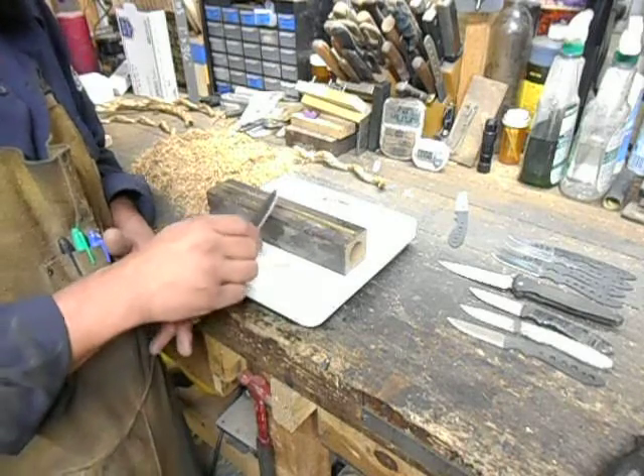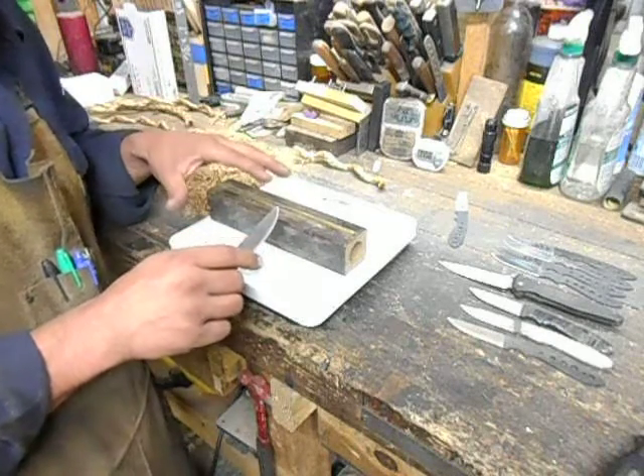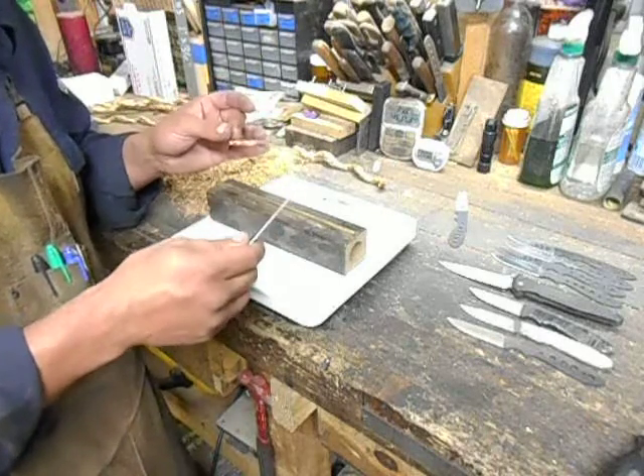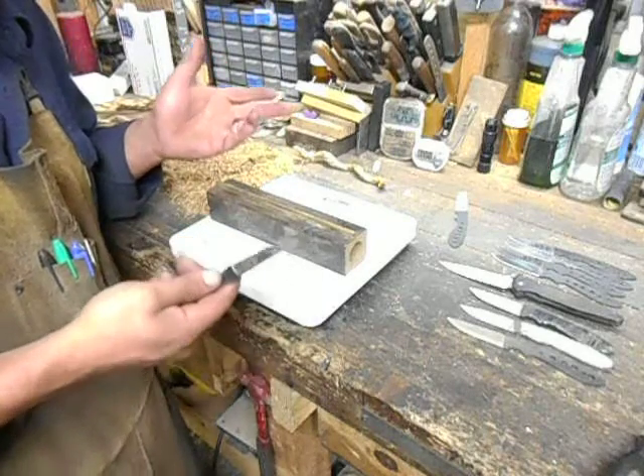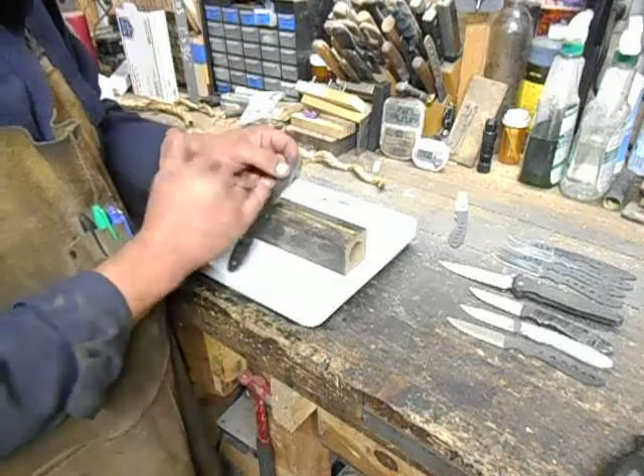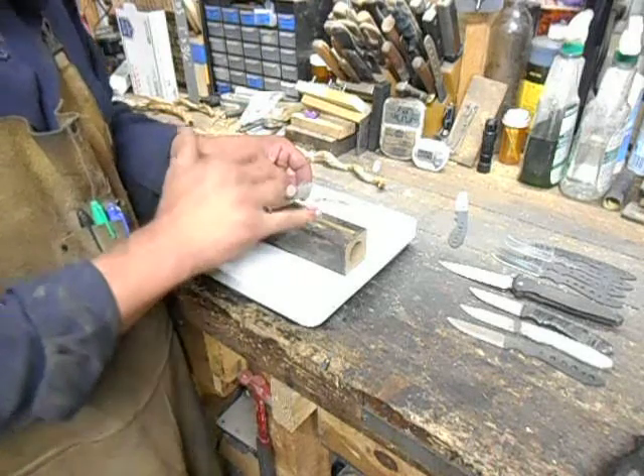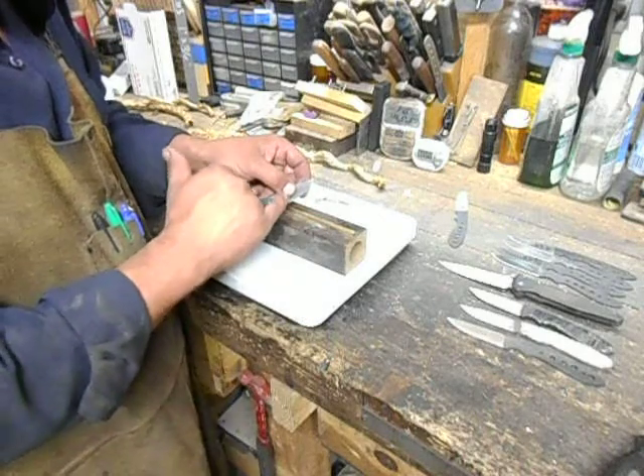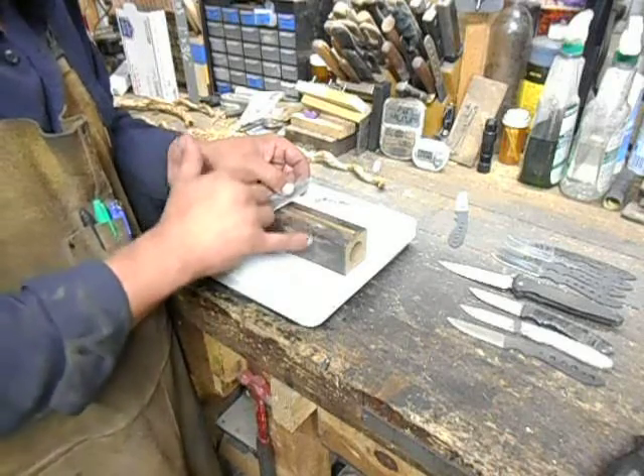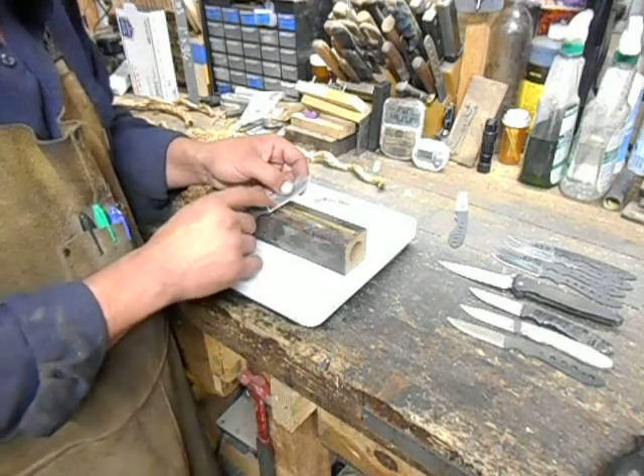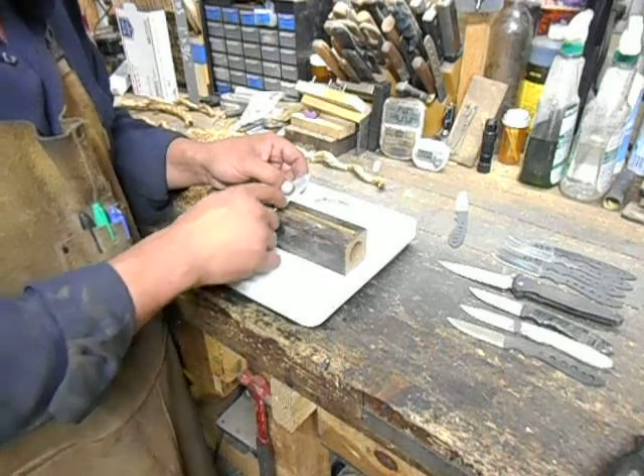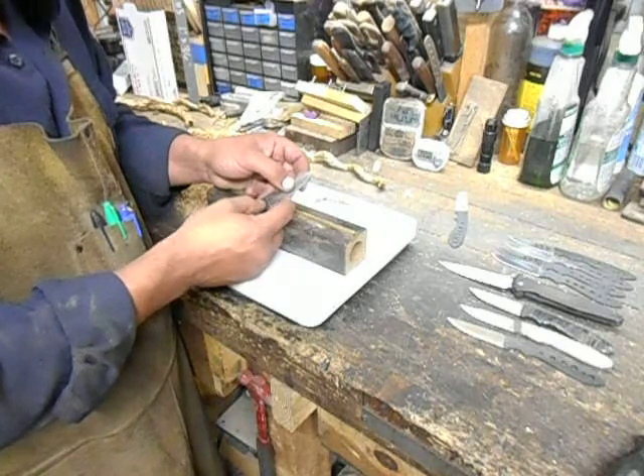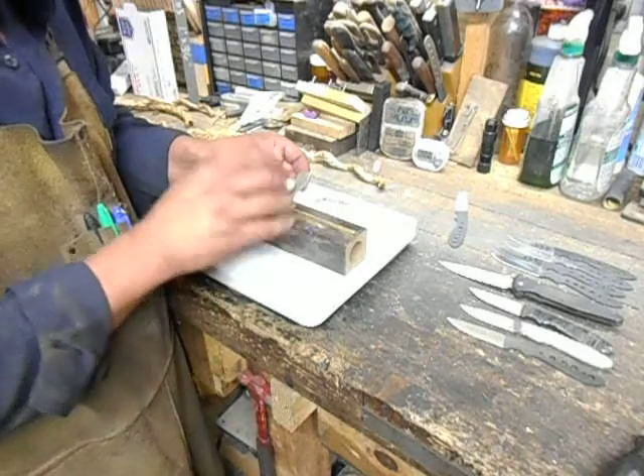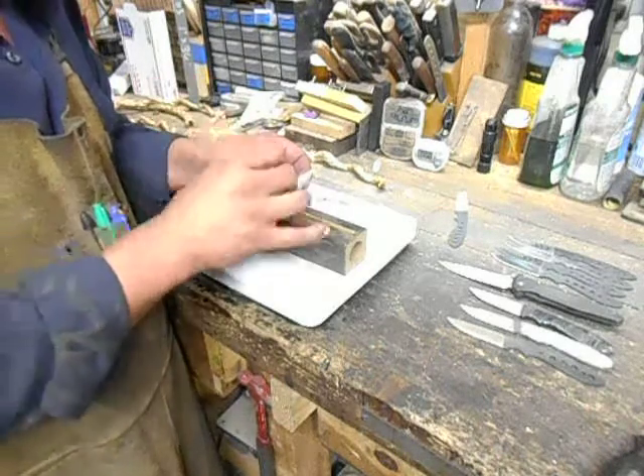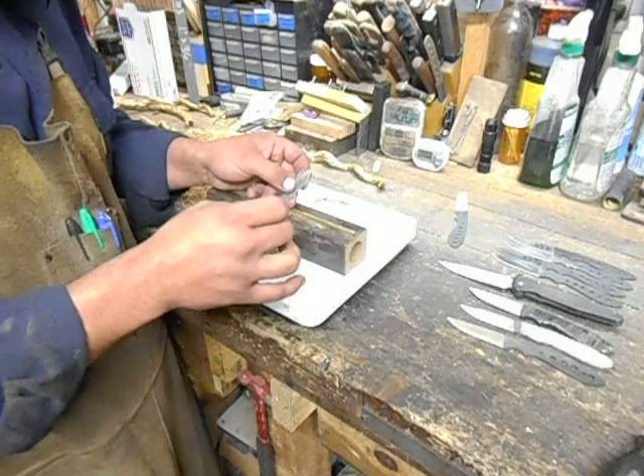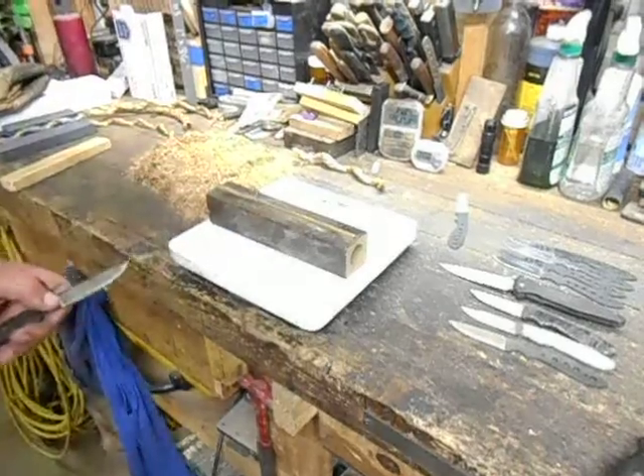Once that edge deforms, you can see it either just by naked eye or you can look at it under magnification. Then you can really start fine-tuning your heat treat to get what I think is perfect. The edge will flex up over that brass rod, and every steel has got an elastic limit. Once you reach that elastic limit and go past it, something will happen to that steel. The best that I have seen is where the edge will not chip, it won't roll, but once you reach that elastic limit, the edge will crack, and that crack will run to the shoulder of the edge and stop. That means that you have got that steel as hard as it can be and no harder, and it's not too soft. Just perfect.